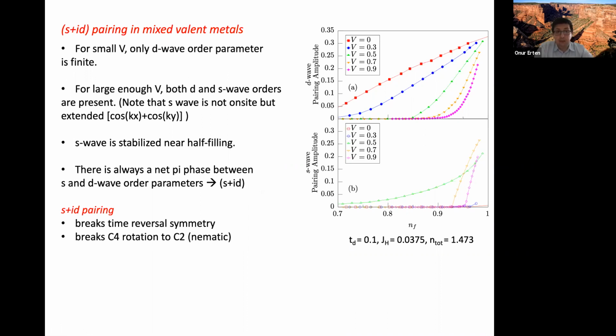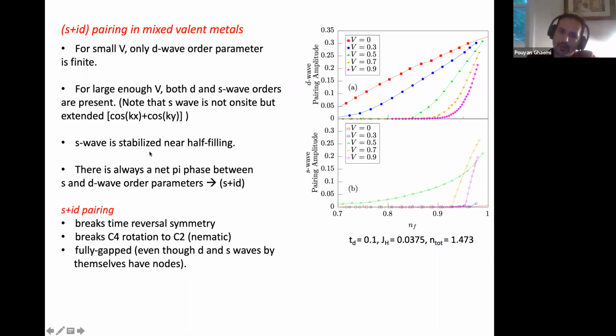It also breaks the point group from C4 to C2. Normally we have a square lattice with a pi by 2 rotation, and this breaks it to C2 rotations. So this is equivalent to a nematic transition. And even though both d and s waves have nodes, s+id, when you combine them in this form, is actually fully gapped. Onur, how does s-wave have nodes? This is cosine kx plus cosine ky. It's extended s-wave. Yes, okay. So even though s and d-wave have nodes, s+id is actually fully gapped.